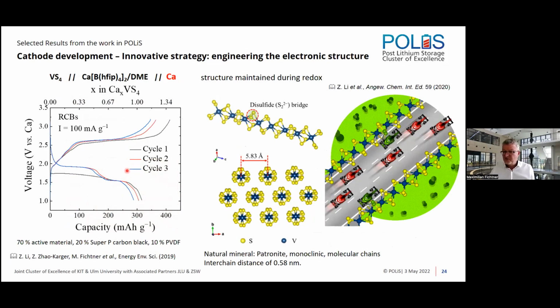The structure of this VS4 is quite interesting. It consists of strands or chains of VS groups here. The blue is the vanadium, and the sulfur is yellow. Here you have these bridged systems. And if you look from the side, you see that there's also space, and this is good for the movement. So you can imagine, this is maybe also the reason why this material is extremely fast. You can imagine that you have race cars, these are our calcium or magnesium ions. They are rushing through these tunnels here, and here on the side you have the strands of the VS4, and then they can dock, can stop, and can either release some charge or get some charge, and then they go on. So this is a nice picture for what is going on there, and this is possible because you get this delocalization.